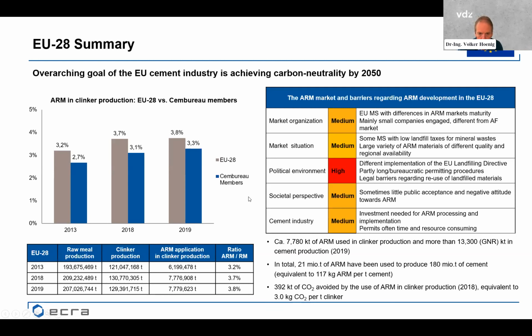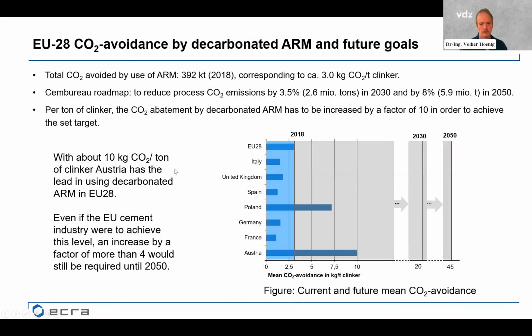With respect to time, I go then to this next slide, which I think is very important. It gives an assessment of CO2 avoidance by decarbonated raw materials on the European level. When we go directly to the graph here, we see Austria with 10 kilograms of CO2 avoided per ton of clinker by alternative raw materials.